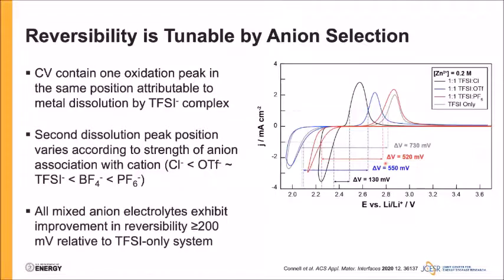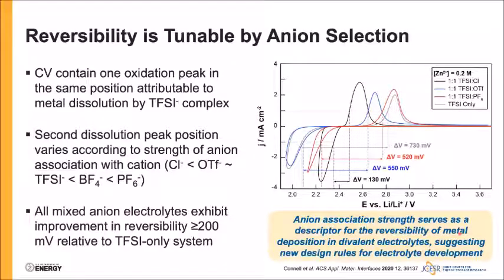And again, as we saw before in the TFSI triflate case, all of these mixed anion electrolytes result in improvements in reversibility relative to the TFSI only case, in keeping with the predictions of DFT, where we see improvements in reversibility of greater than 200 millivolts for all the mixed anion electrolytes we studied. And so what this tells us is that anion association strength can really serve as a descriptor for reversibility of metal deposition. And more importantly, it suggests a new set of design rules for electrolyte development.